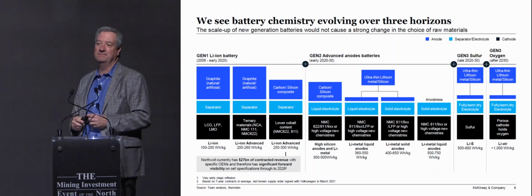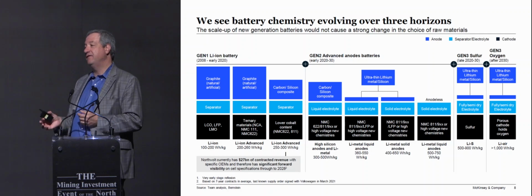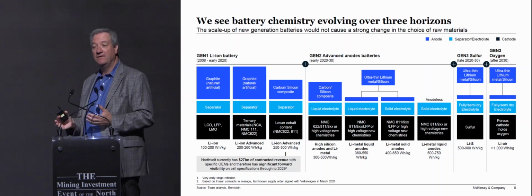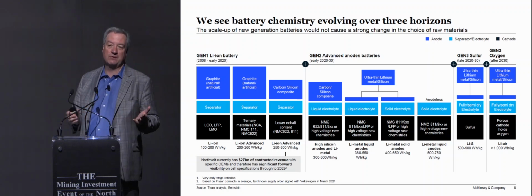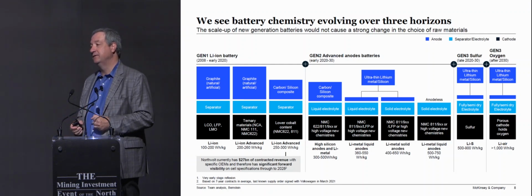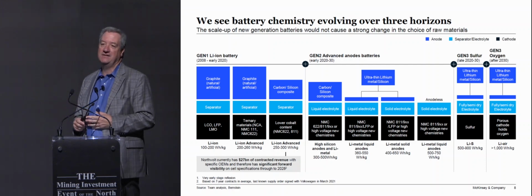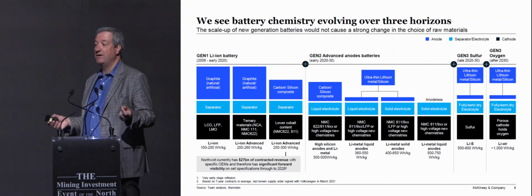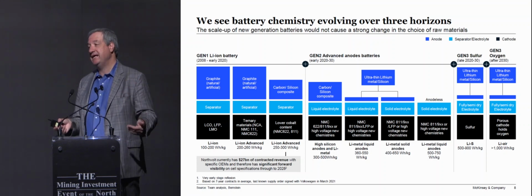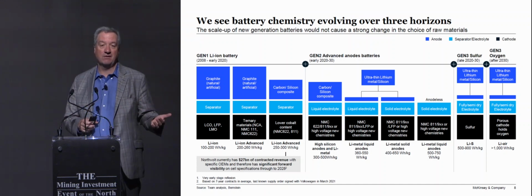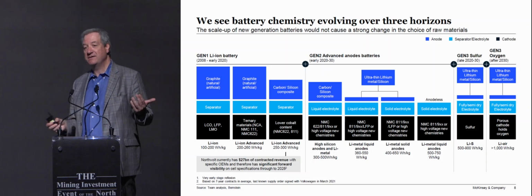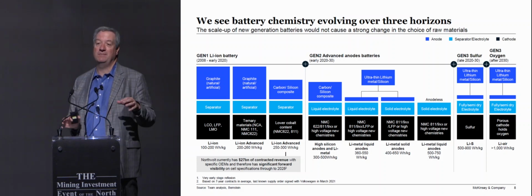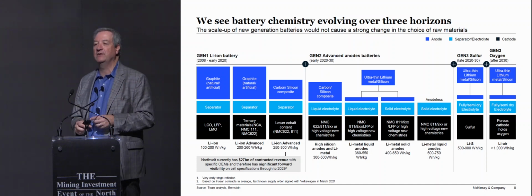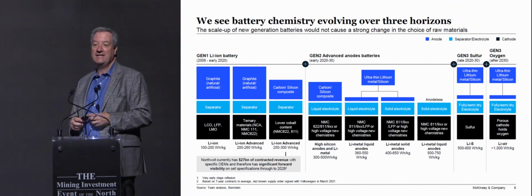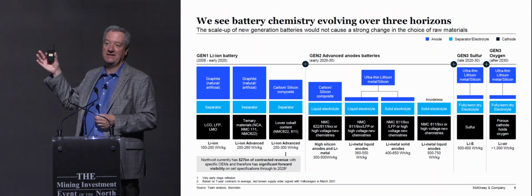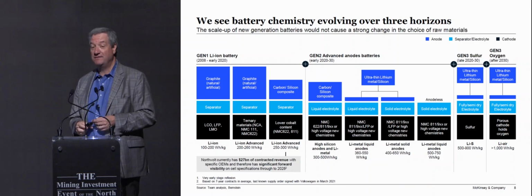If we look at companies like Volkswagen or Tesla, they are using high nickel batteries in their cars. Those can have much, much higher densities, on the order of 260 to 290 watt-hours per kilo. And so again, one of the reasons why you've seen virtually every new cell plant being built in North America, at least announced to date, they're all high nickel batteries. And all of the ones in Europe, except for two, are high nickel batteries. That's about 100 new cell facilities in North America and Europe that are planned on being built. They probably all aren't built, but they're all high nickel batteries. And so that's giving you that density you want. It gives you the range that your consumer wants, but it's an awful lot of nickel.